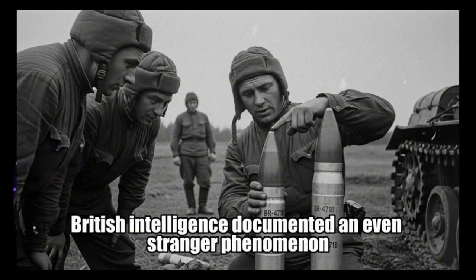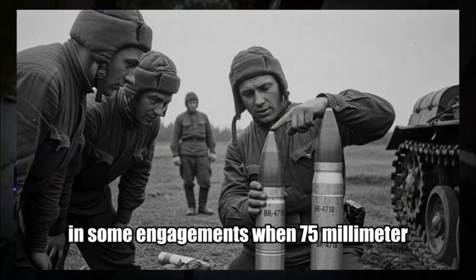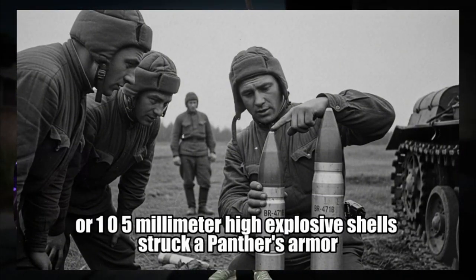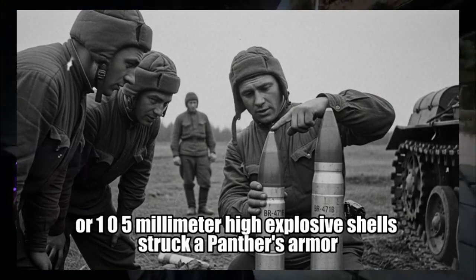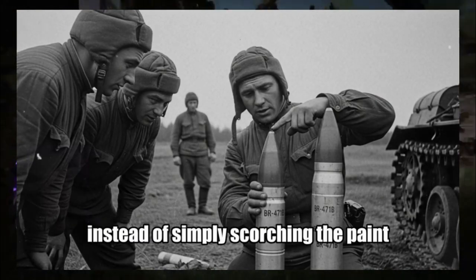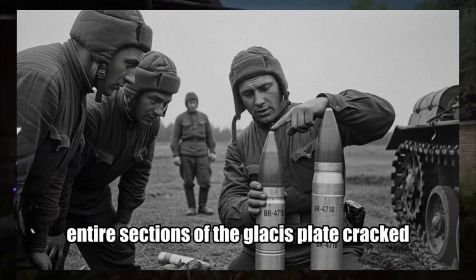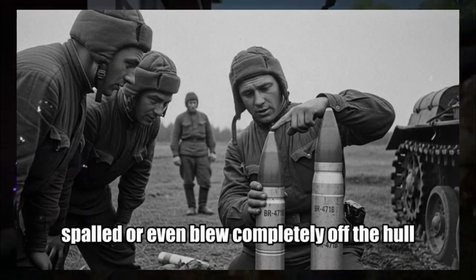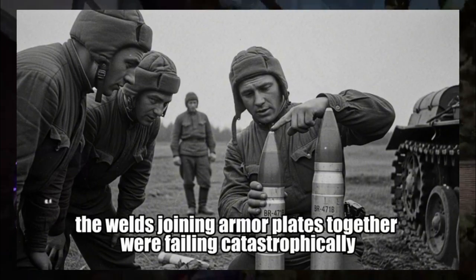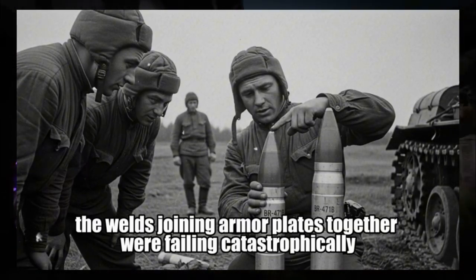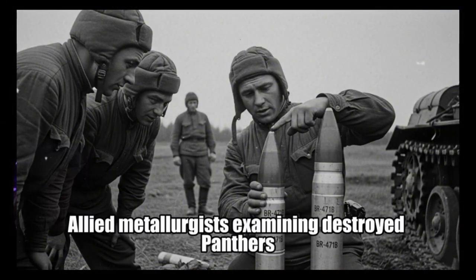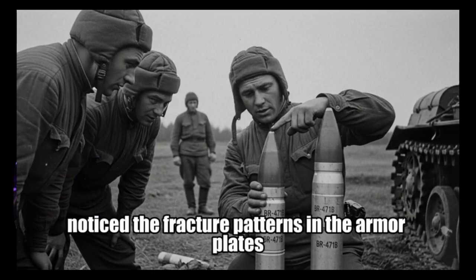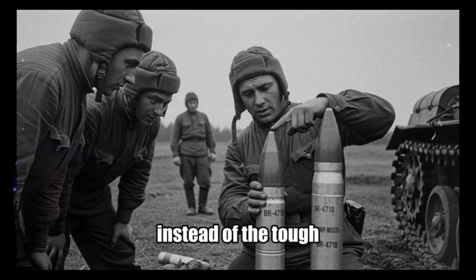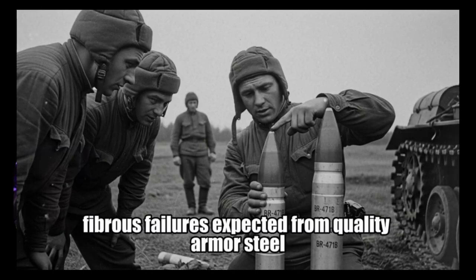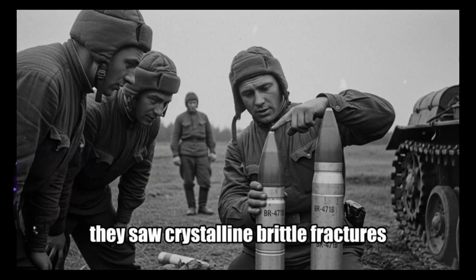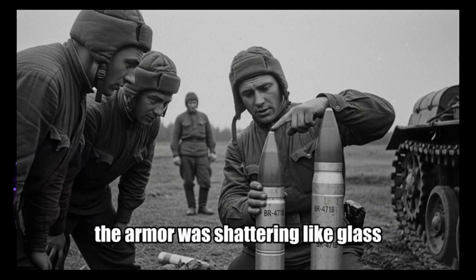British intelligence documented an even stranger phenomenon. In some engagements, when 75mm or 105mm high-explosive shells struck a Panther's armor, instead of simply scorching the paint, entire sections of the glacis plate cracked, spalled, or even blew completely off the hull. The welds joining armor plates together were failing catastrophically. Allied metallurgists examining destroyed Panthers noticed the fracture patterns in the armor plates. Instead of the tough, fibrous failures expected from quality armor steel, they saw crystalline, brittle fractures. The armor was shattering like glass.